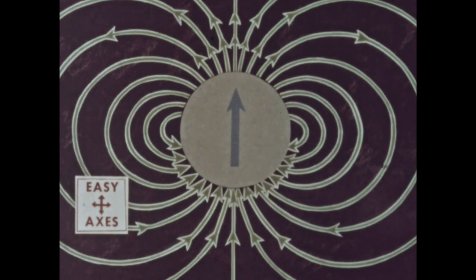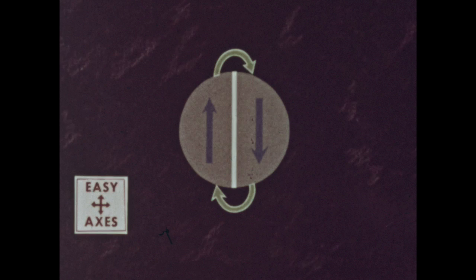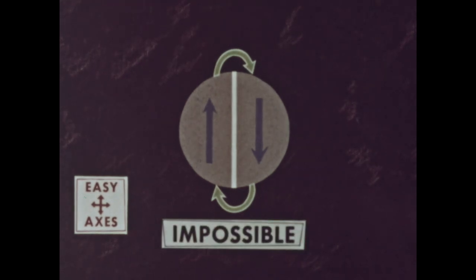The formation of smaller domains, which would decrease the magnetostatic energy, is impossible, because the creation of a very thin domain wall would be necessary. Such a wall would contribute so much exchange energy that the total energy of the particle is less when it is saturated.